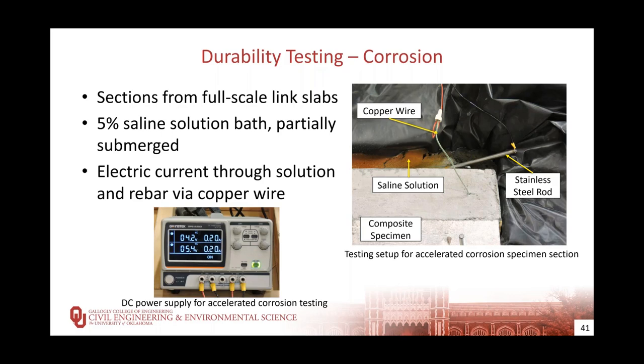The surface top will be placed down into the bath, as this surface is where the cracking will be most severe, as well as that which would be exposed to chlorides on an actual bridge deck. An electric current will be passed through each specimen and solution.